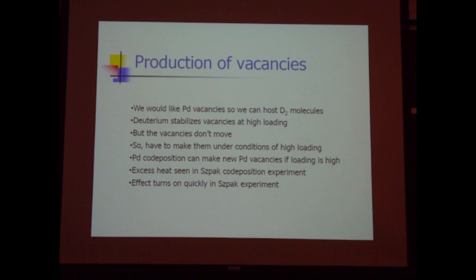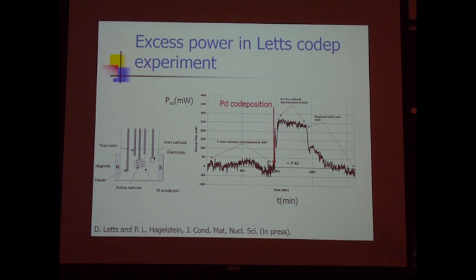So maybe this is an explanation for the SRI curve, that if a cathode reaches a loading of 0.95, if there's some inadvertent palladium co-deposition, you get some vacancies, and you can do your business. I had mentioned that last time when I was zipping through all this stuff, the Letts experiment. So Letts, Cravens, and others had tried the Szpak co-deposition protocol. Now, Szpak didn't publish his protocol, but at Speyworth, where the work was done, Pam Boss had been publishing a version of the Szpak protocol, which involved running at very low current density. So she would run at low current density in order to have the palladium adhere to the cathode surface. And if you crank the current density up under those conditions, then the palladium deposits much faster, and it doesn't deposit very well. It falls off and collects at the bottom.